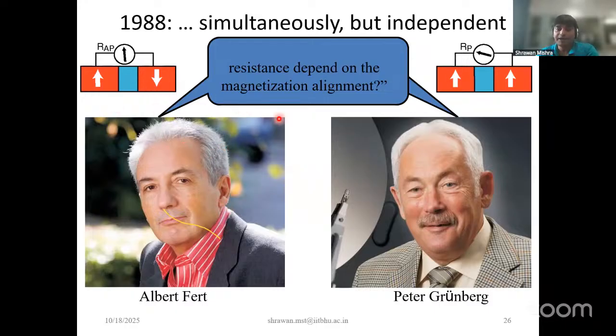This leaves behind a new phenomenon that is called GMR. Depending on the magnetization arrangement of these two ferromagnetic layers, the overall resistivity that you measure in these two cases will differ. And this difference in resistivity you can control by changing the magnetization of a material. So ultimately, you are affecting the transport behavior of a material by changing the magnetic field. That's a unique observation that these two people showed. And for their work in 2007, they were awarded the Physics Nobel Prize.